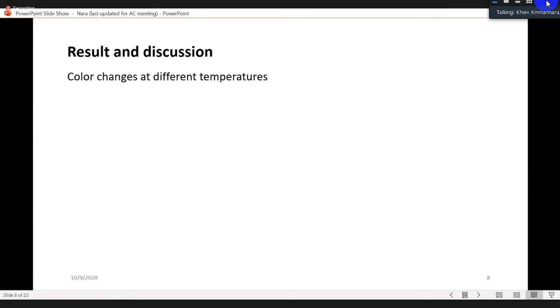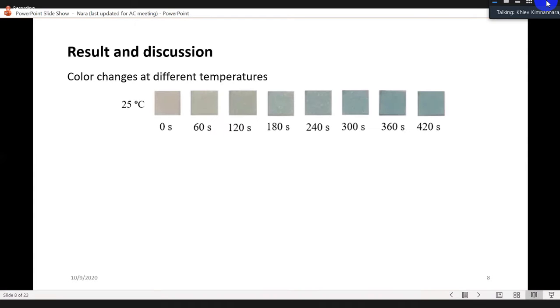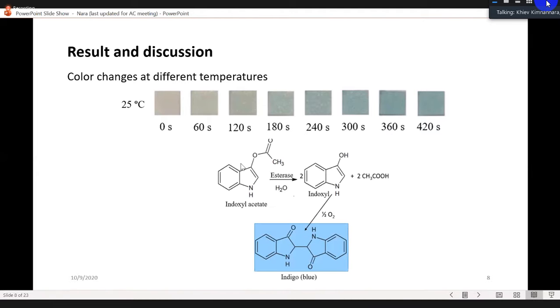Result and discussion. In this part, I will explain the color changes at different temperatures. First, at room temperature, we can see that the color changes from colorless to greenish blue and then from greenish blue to blue. It means that the reaction happened, indoxyl acetate was hydrolyzed by esterase and converted to indigo blue like this. However, I feel the reaction at room temperature is not so fast.